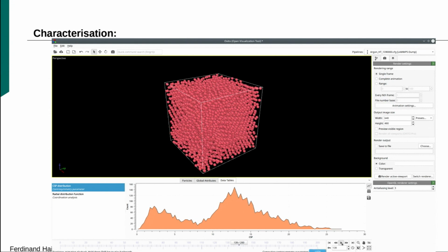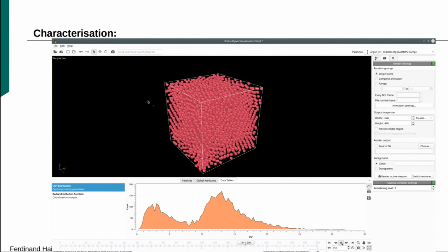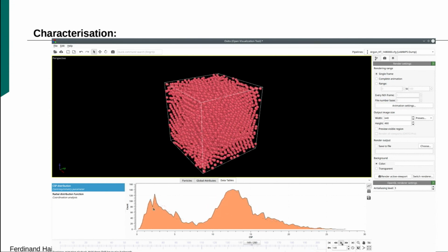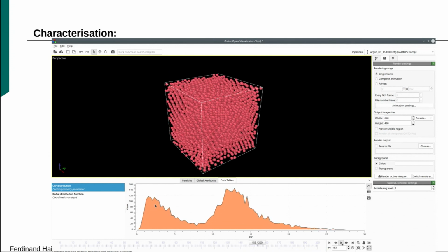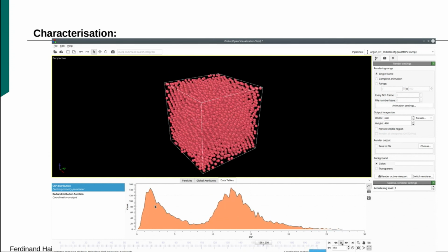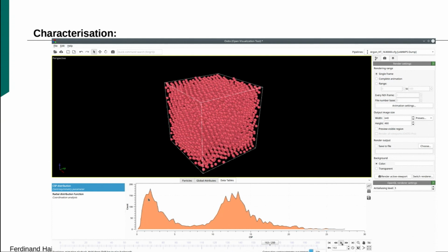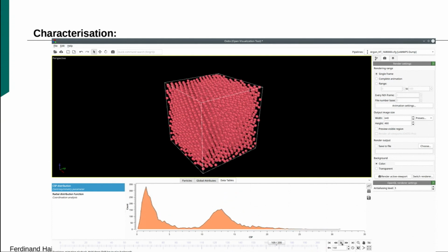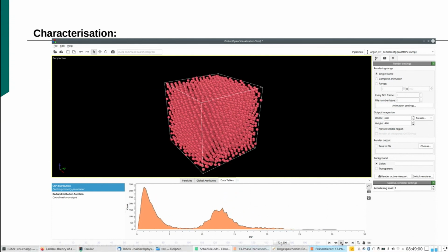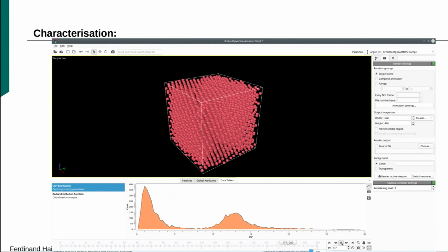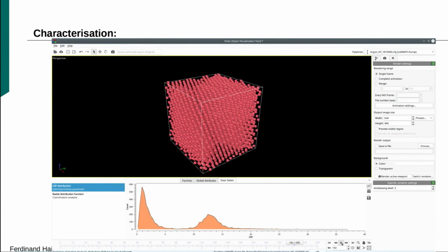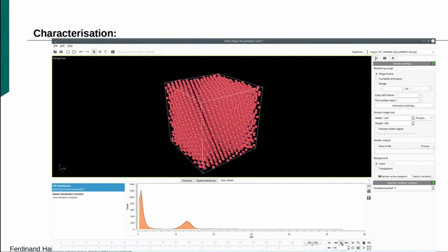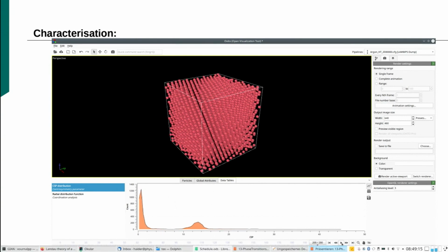Now you see that the crystallization sets in here, for example, and here you see that the maximum in this centrosymmetry parameter close to 0 builds up. So this FCC structure is centrosymmetric, while the molten structure is random. And now here at very low temperature, you see nicely the crystal structure here, and this other part completely vanishes.